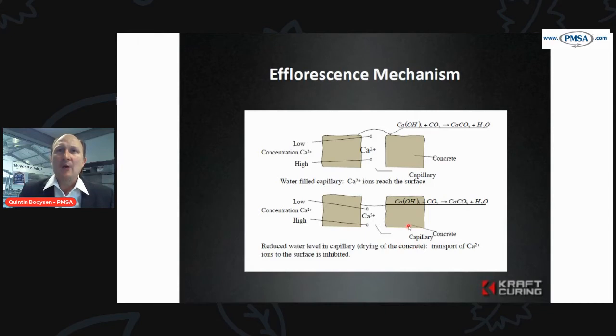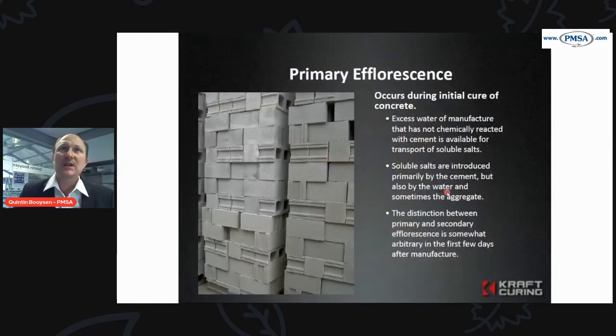So if we can reduce the migration of the salts to the surface, we effectively can halt or greatly reduce the efflorescence on the surface of the concrete, because the free lime or the calcium hydroxide just doesn't have a chance to be transported to the surface. It doesn't have a chance to meet with the carbon dioxide and form this calcium carbonate. So effectively, what we try to do is have as dense a product as possible that would reduce the amount of water, or the free water in the system, that would ultimately reduce the calcium hydroxide moving to the surface.